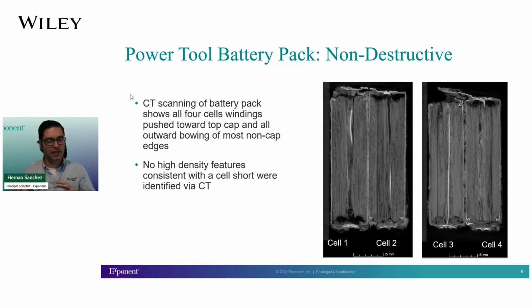It's one piece of the puzzle, and all of these investigations are really puzzles. You go gathering evidence, and with that you come up with the best understanding that you can of the failure mode of what happened, right? In this case, we were not finding any high density features. So now that we have the CT data stored, we were able to push towards the destructive testing.